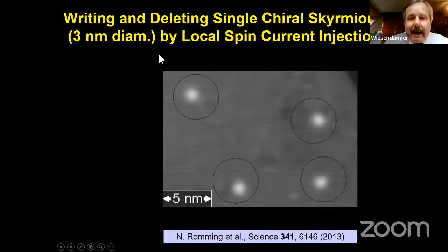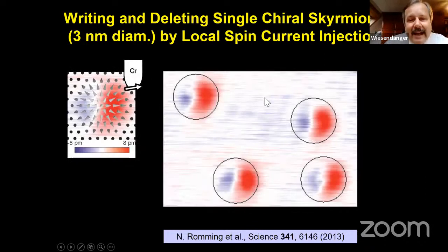This is again the palladium iron bilayer on iridium-111. Here are 4 atomic defects. Notice the extremely small scale. These atomic defects are due to exchange processes between palladium and iron atoms. We used these atomic scale defects to pin skyrmions after their creation, because individual skyrmions are quite mobile. So we have to pin them at these atomic scale defects, and we can do so. So we can create skyrmions here, as you see now as additional contrast. We can just calculate the difference image of the two data sets, and now we can beautifully reveal the magnetic state of these 4 skyrmions, which we have created.